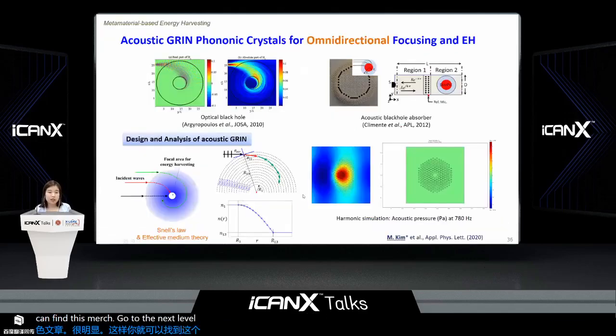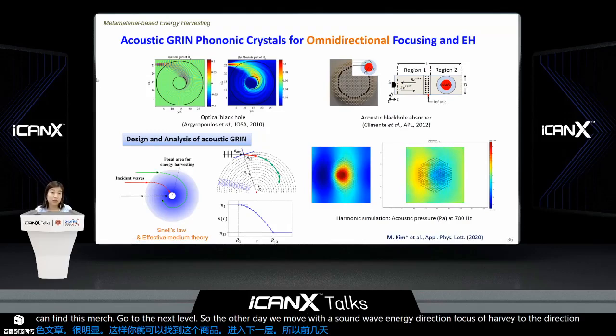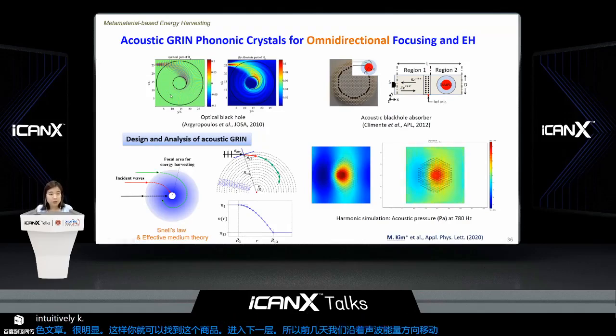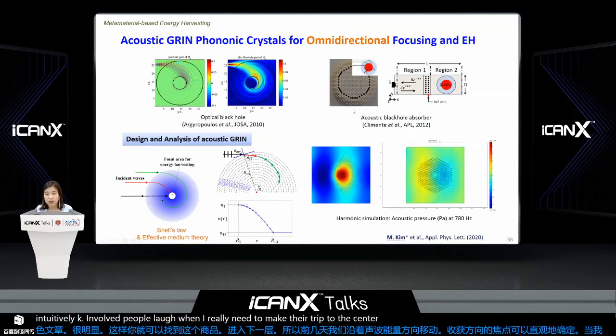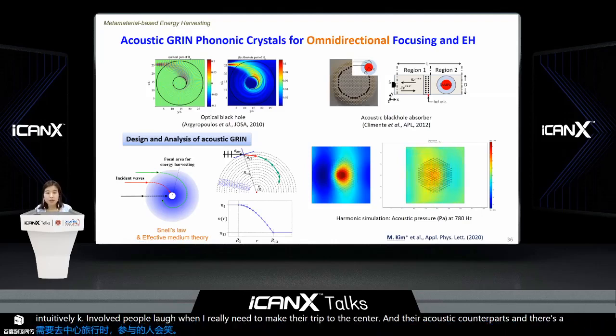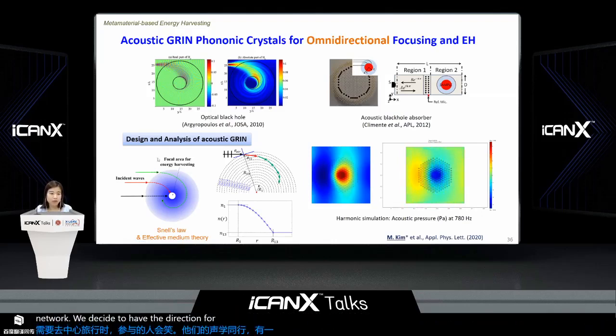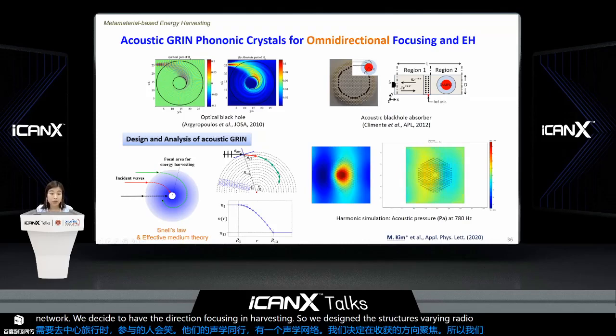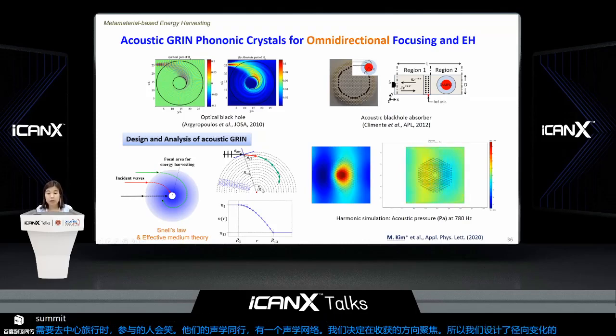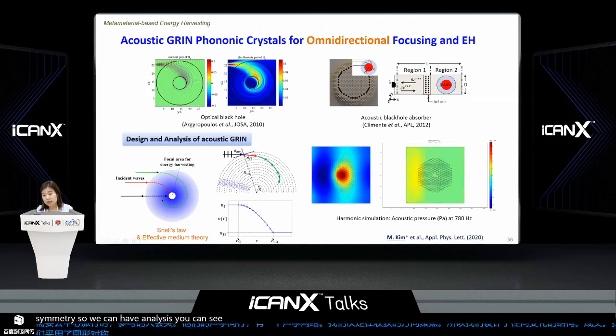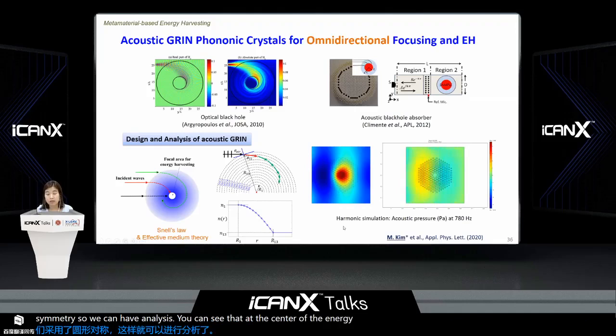The other thing we looked at in using sound wave energies is omnidirectional focusing and harvesting. For omnidirectional, as you can intuitively think of, there's an optical black hole, like a black hole really. Electromagnetic waves come in and they are trapped at the center. And there's an acoustic counterpart to this, an acoustic black hole. We adopted this idea to have omnidirectional focusing and harvesting, so we designed the structures by varying radially the refractive index, and we adopted circular symmetry so that we can have omnidirectionality. And in harmonic analysis, you can see that at the center, the sound energy is focused. And this article is published this week too.